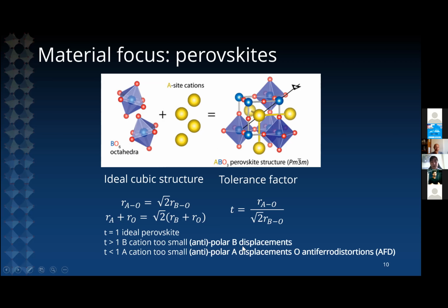So in this case, you will allow for a number of antipolar or polar displacements of the B cation. So that's a typical situation of ferroelectric materials. Or if you're trying to accommodate an ion that is, for example, a cation that is too small, then you will generate a number of antipolar or polar displacements of the A atoms. And this is accompanied by also antiferrodistortive motions of the oxygen octahedra. So many types of structural distortion that can be accommodated by the perovskites with various cations.